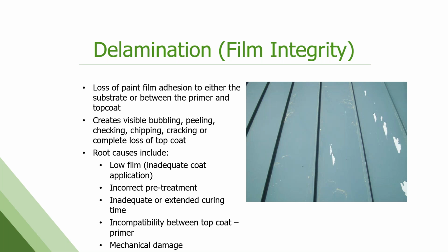And the root causes are, like I said, lots. These are the most common ones. We didn't put enough film on it during the application process. We had an incorrect pretreatment, inadequate or extended curing. So when you cure these paints, if you under-cure them, they're going to fail in the field. If you over-cure them, they're going to fail in the field. So you've got to hit the sweet spot. An incompatibility between top coat and primer. And this is a big one: mechanical damage inflicted on the roofs, either during installation or sometime during their life.